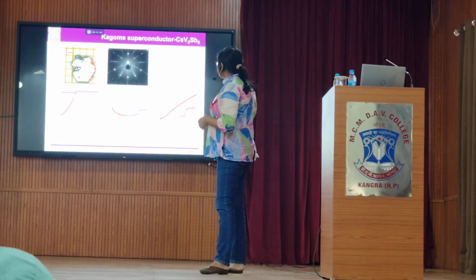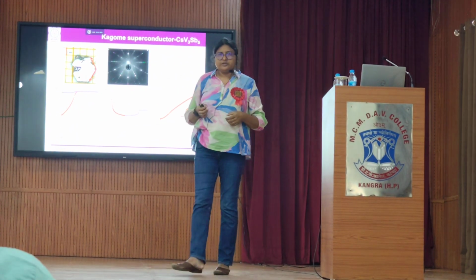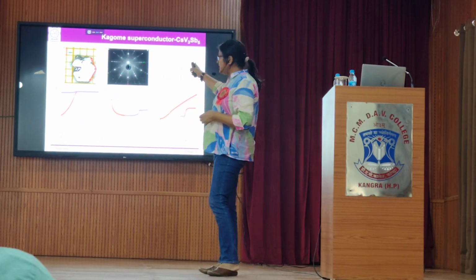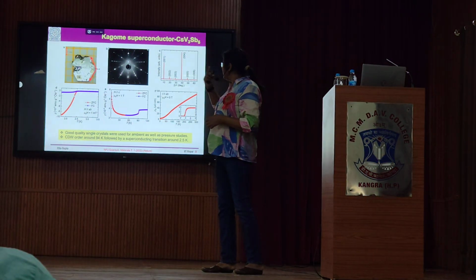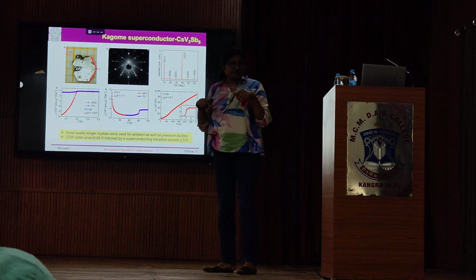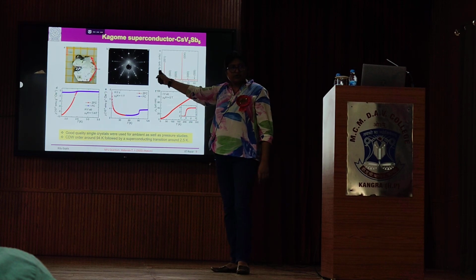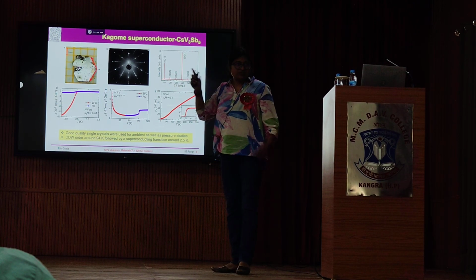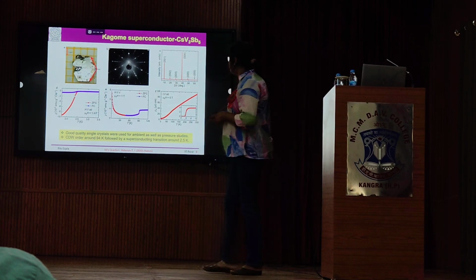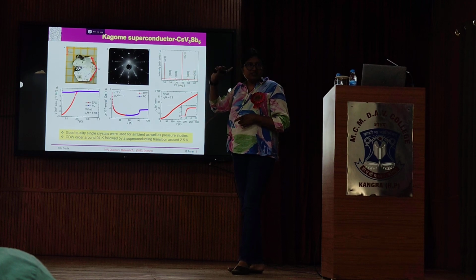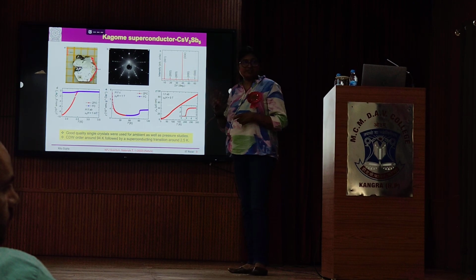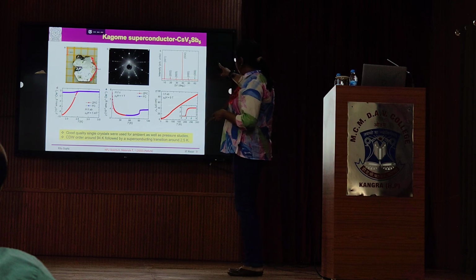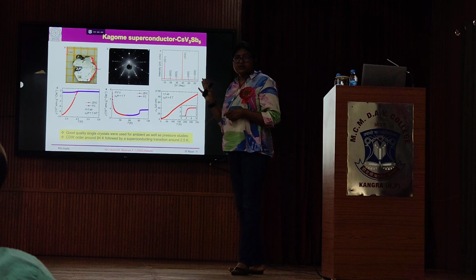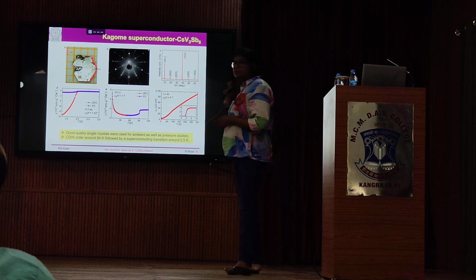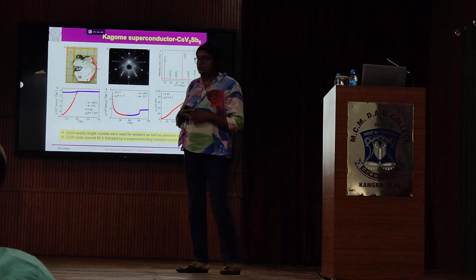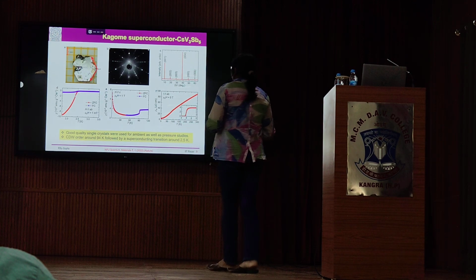Okay. So now coming back to the material which we started talking about. So this material is actually grown in the lab. You remember it has a hexagonal type of structure, and if you look at the crystal shown in the first picture, this is the optical picture just taken by a camera on millimeter scale paper. So you can see a clear hexagonal symmetry of that crystal, and you see how beautiful the crystal is looking. Okay, and the second picture is the Laue picture, which is one of the methods to determine the symmetry of any crystal. So you can see clear hexagonal symmetry there also.